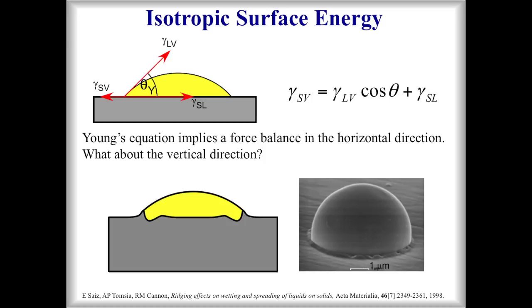Actually, we've shown this experimentally several times. Not only we, several people, by sectioning small droplets in half. And here's a nice little example where you can see the ridge without even touching the particle. But if you were to section that in half, you'll see a small trough adjacent to the ridge. And actually, this is just the Mullins equation. This is grain boundary grooving, exactly that, rotated 90 degrees.